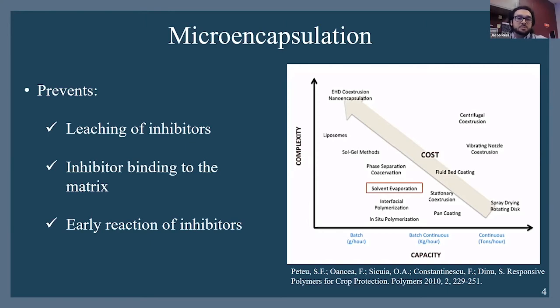And in this plot by Peteu et al., we can see the various forms of microencapsulation that have been used for corrosion inhibitors recently, as a function of capacity, complexity, and cost. So in our journey to create a microcapsule that can be cost effective and scalable for the industrial scale, we've chosen the solvent evaporation technique. Being able to use this microencapsulation, we can avoid the leaching of inhibitors in the concrete, as well as the premature binding of our inhibitors in the matrix and any other early reaction with the concrete matrix.